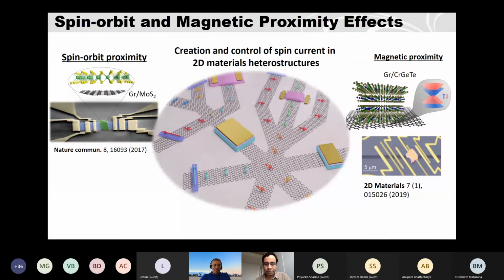So 2D ferromagnets need to be grown by maybe MBE, and then one needs to encapsulate them somehow. That is quite a tricky part. But I saw some papers with synchrotron ARPES measurements on bulk van der Waals ferromagnets. For example, they just take the bulk material, cleave it from the top and study it. We are also doing some similar measurements in collaboration at MAX Lab in Lund.